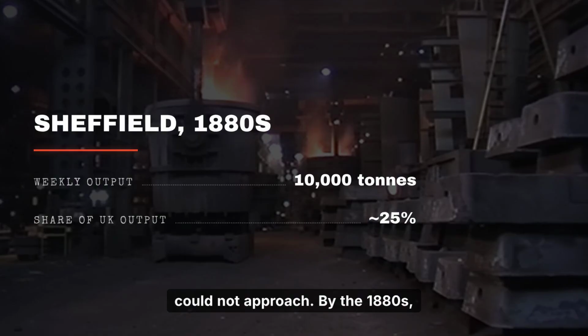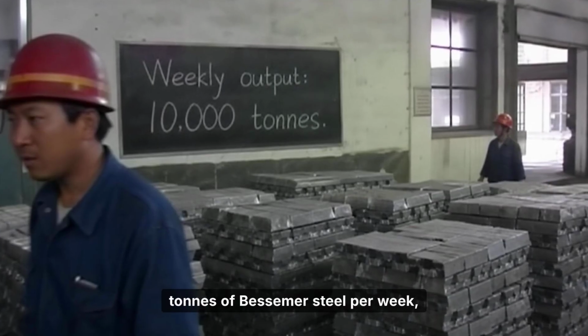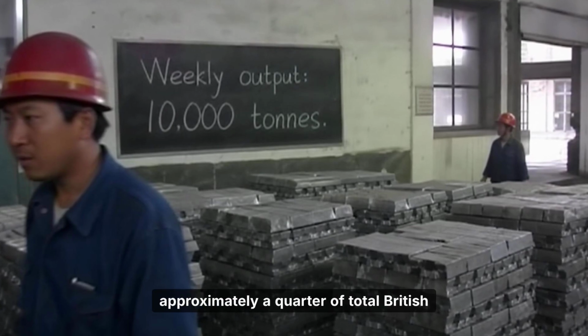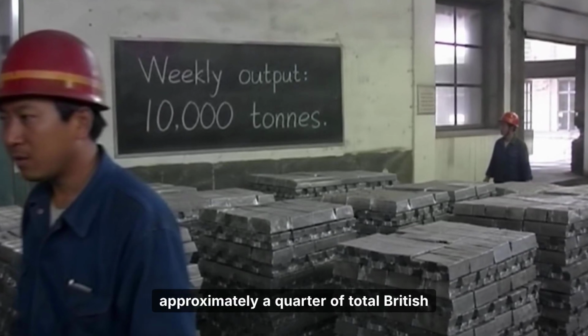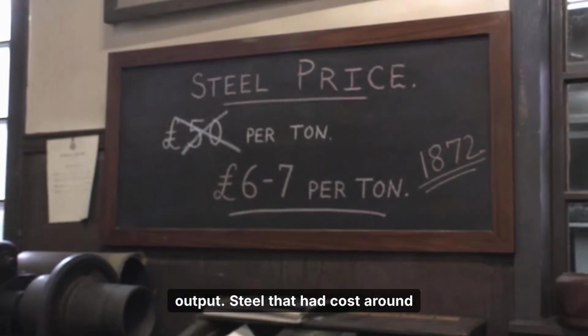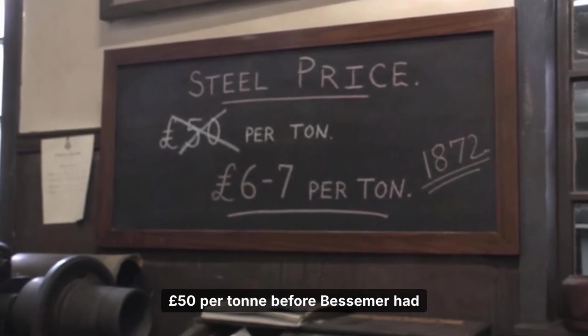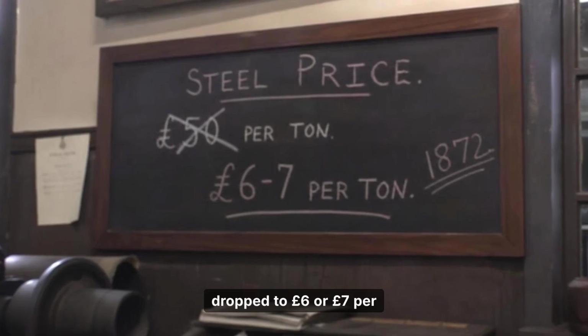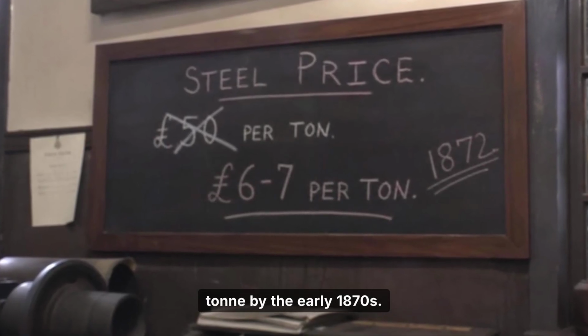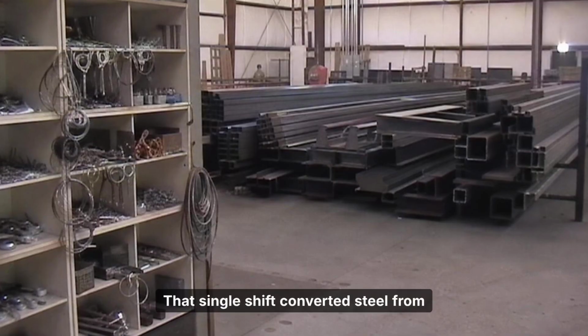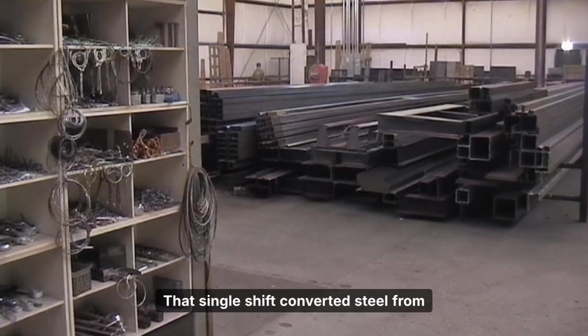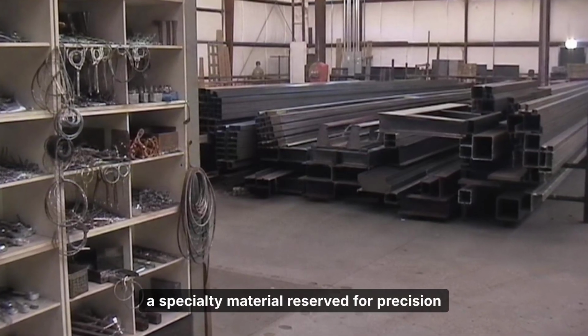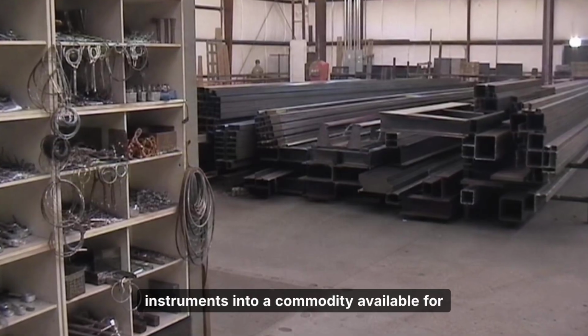By the 1880s, Sheffield alone was producing roughly 10,000 tons of Bessemer steel per week, approximately a quarter of total British output. Steel that had cost around £50 per ton before Bessemer had dropped to £6 or £7 per ton by the early 1870s. That single shift converted steel from a specialty material reserved for precision instruments into a commodity available for large-scale construction.